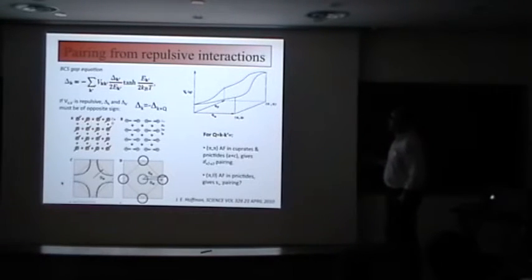It's quite simple if one looks at the BCS gap equation. If V is attractive, meaning V can be negative, this minus sign cancels that minus sign, and we get a solution to the gap equation where delta is just a number or mildly K dependent. But if V is repulsive, meaning connecting state K to K prime is always positive, then the only way to satisfy the gap equation is by having the gap change sign.